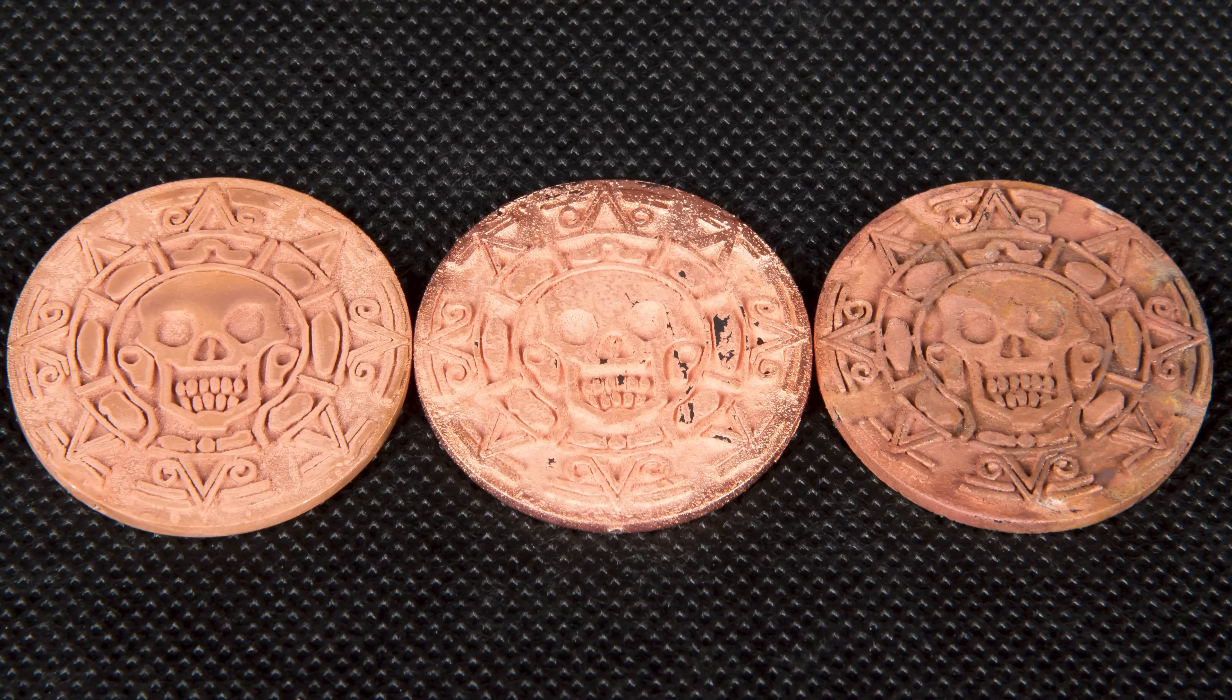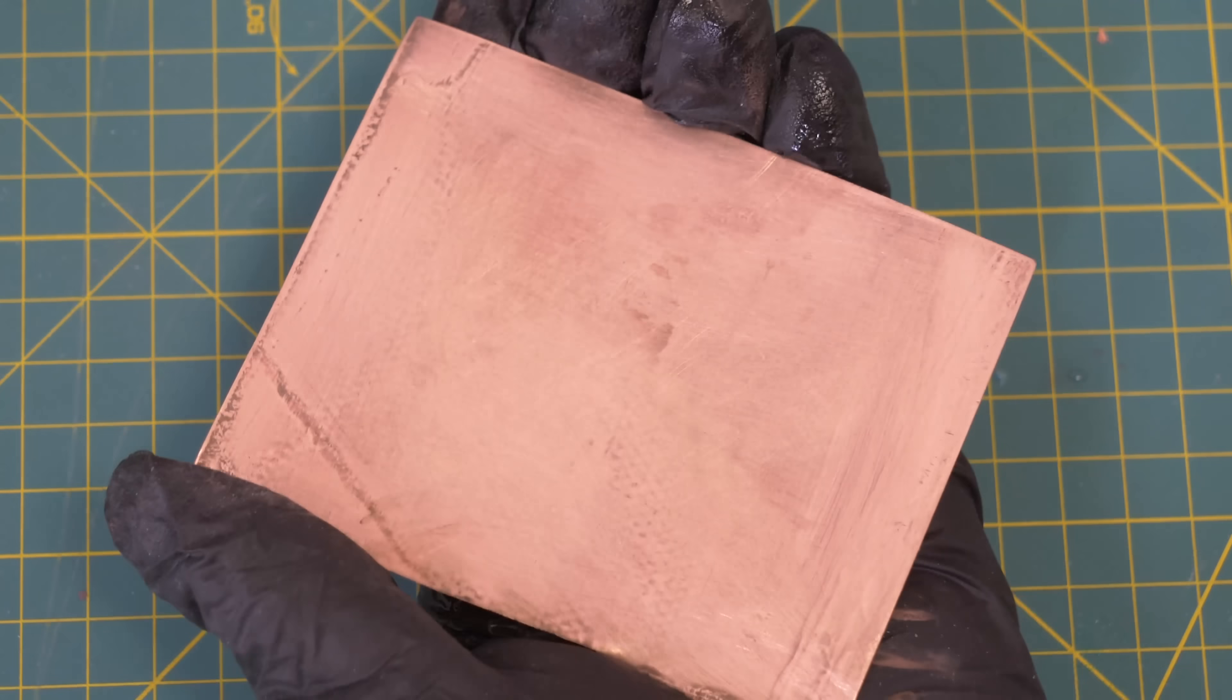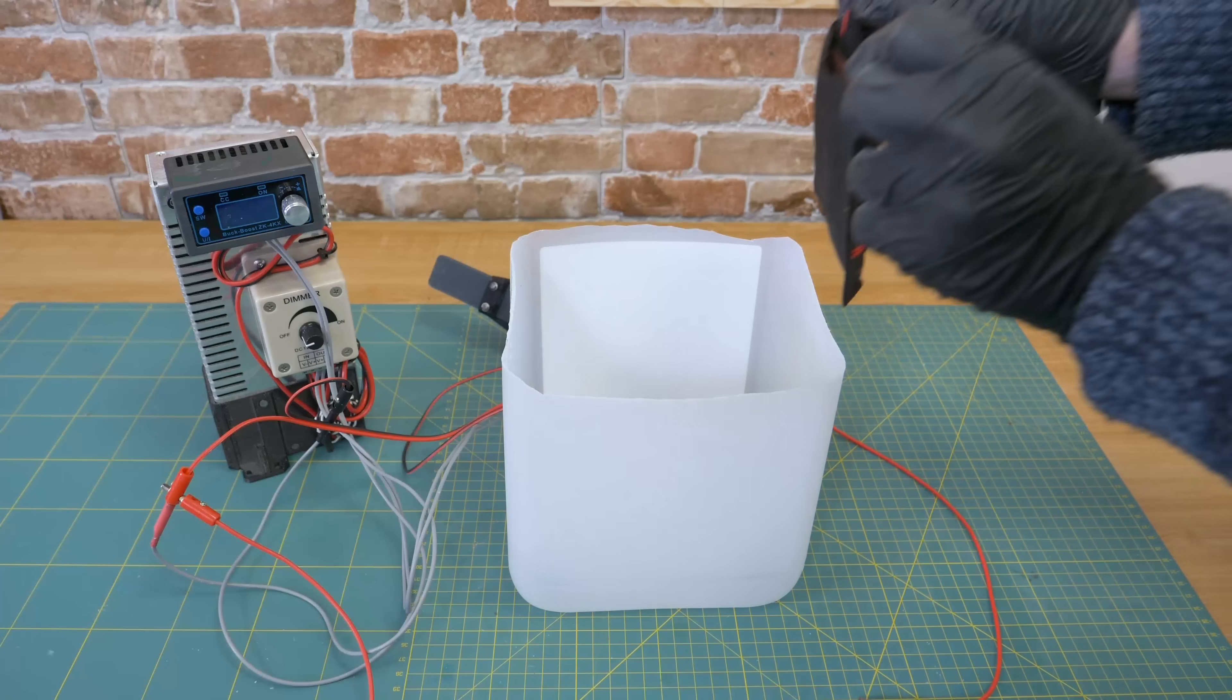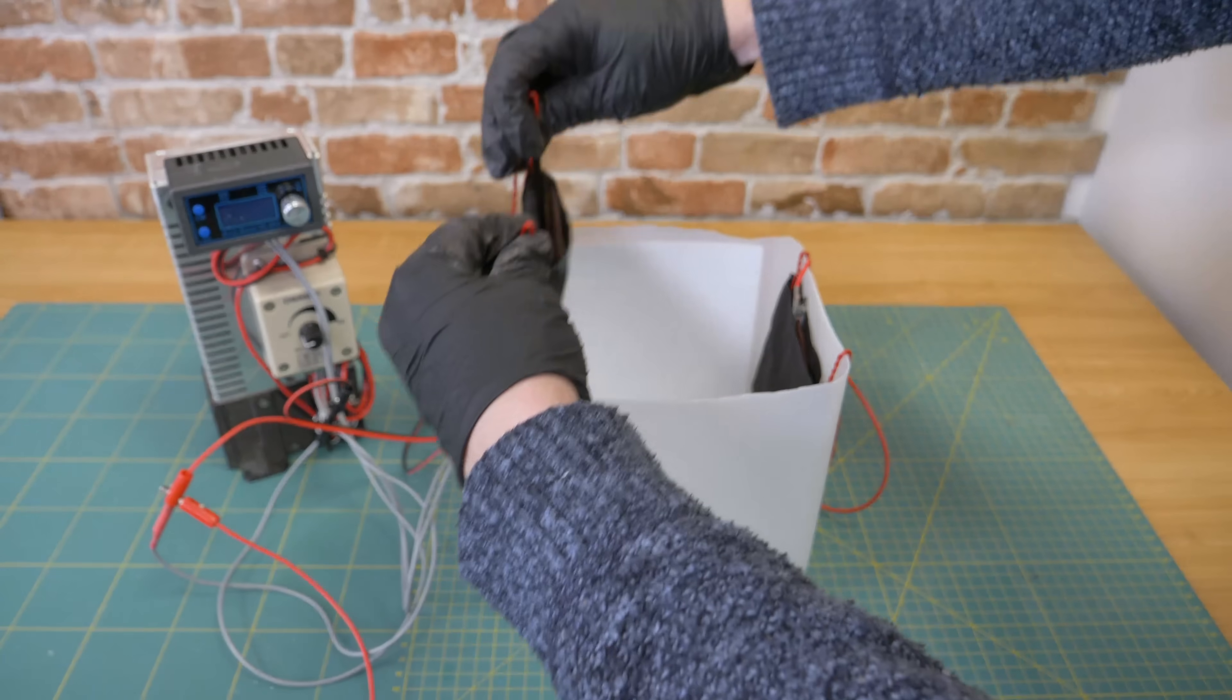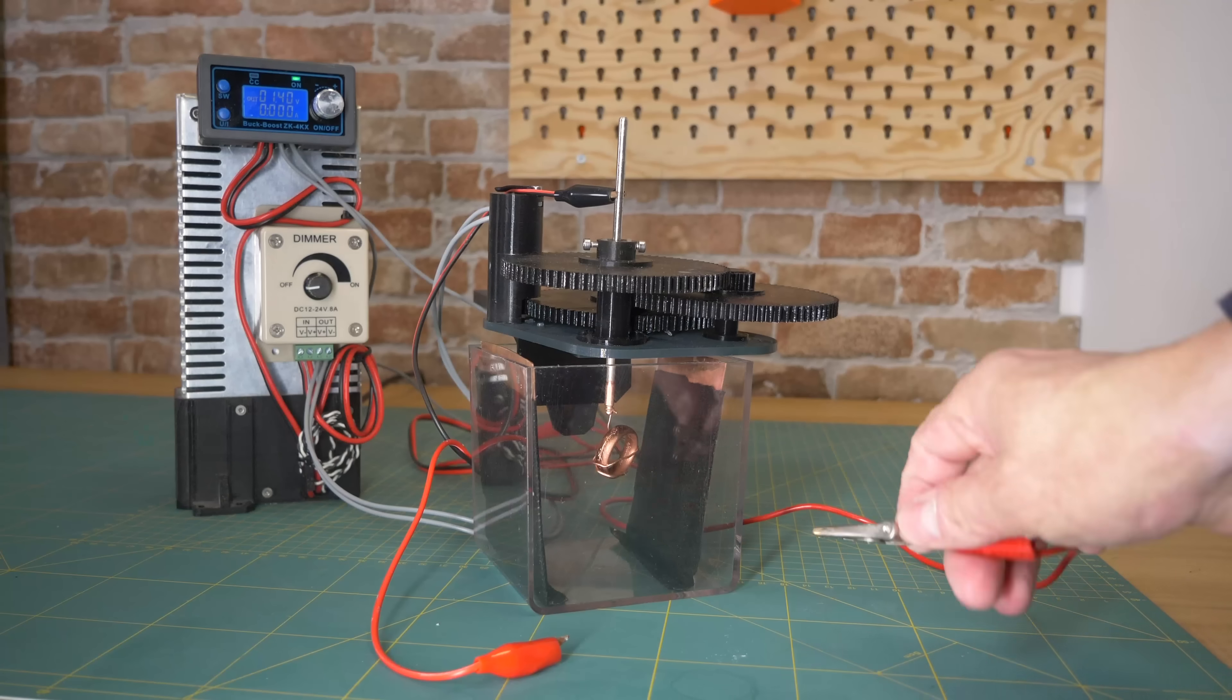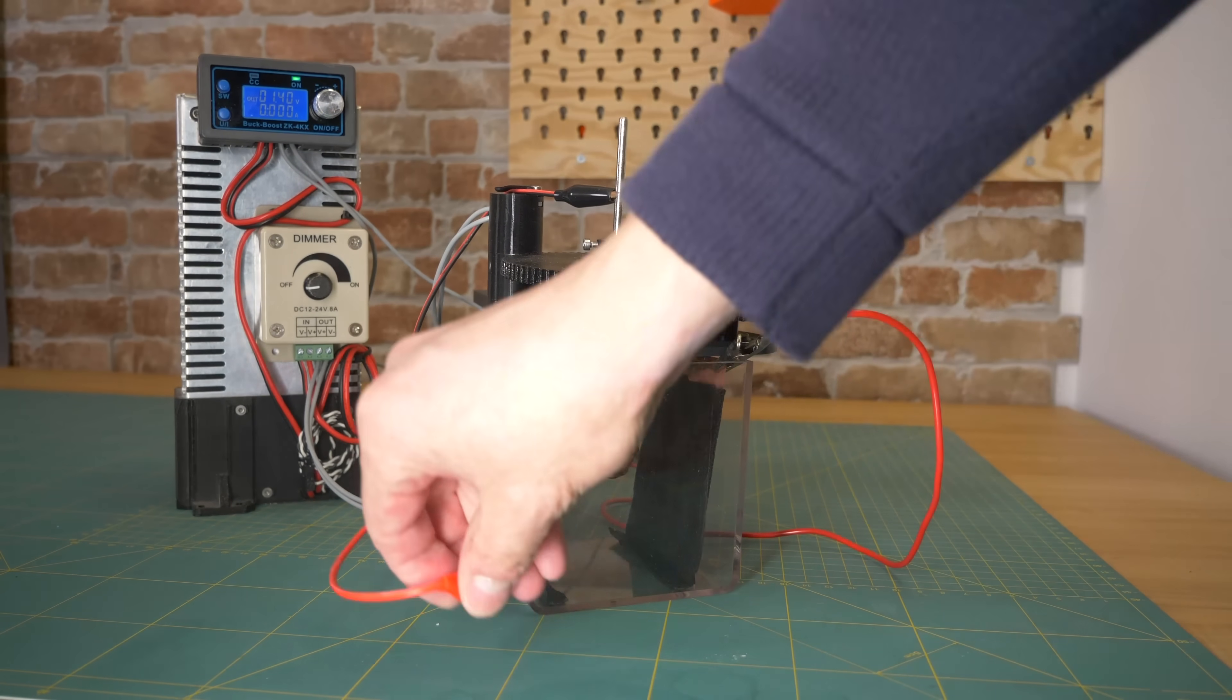Okay, now let's prepare the gear. First clean the anodes with steel wool or a piece of fine sandpaper. Then carefully place the anodes inside the tank. We recommend putting them inside textile mittens or pouches to prevent any particles from falling off the anodes.